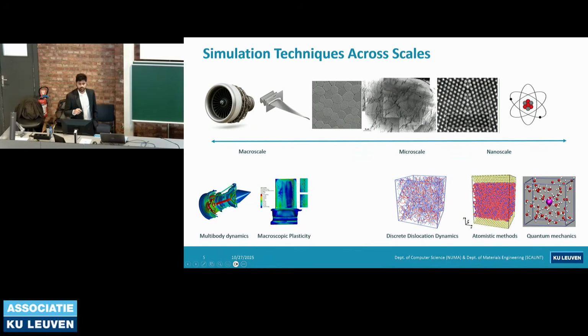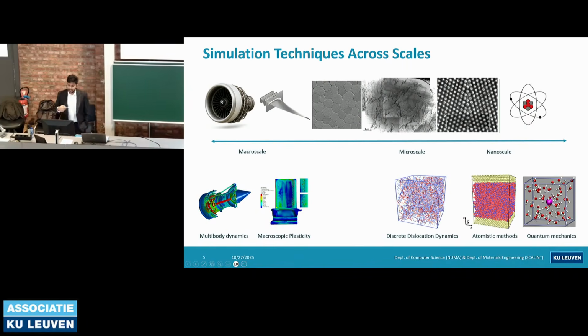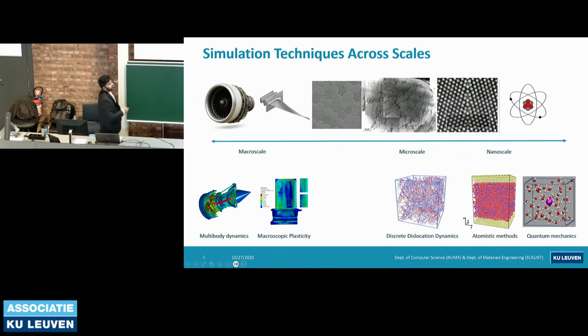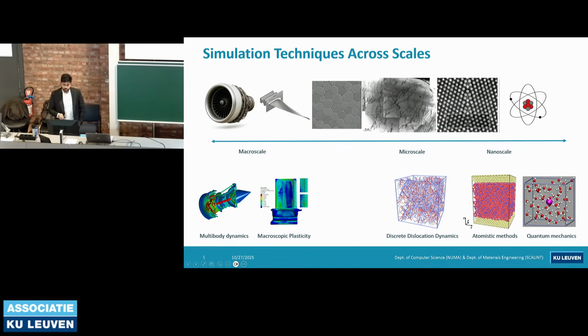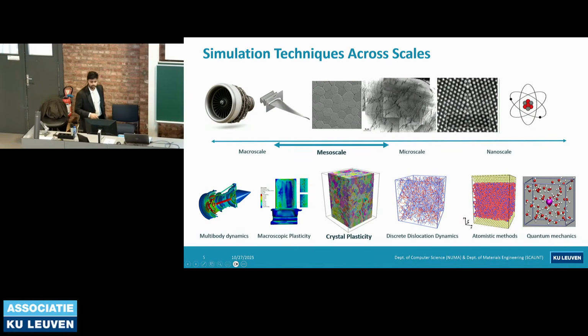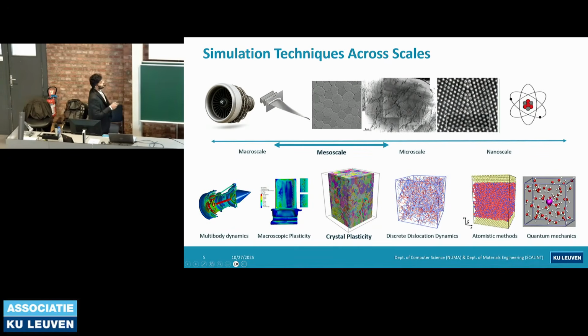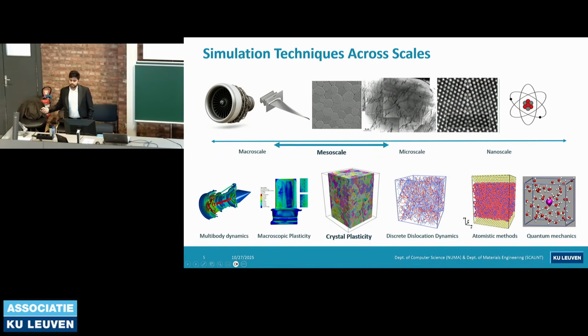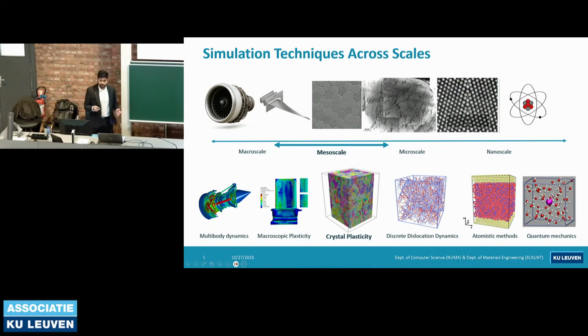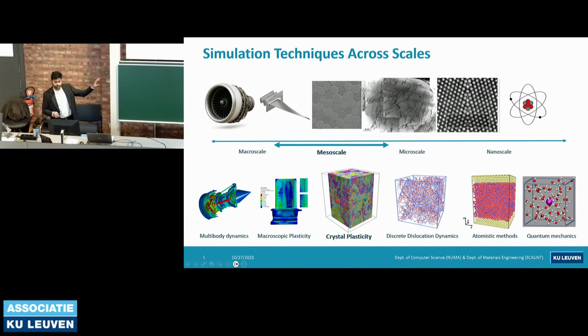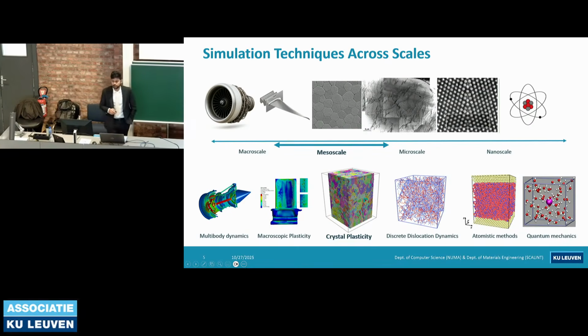But clearly, the simulation techniques on this end are quite practically applicable, and they can reproduce the realistic boundary conditions which are actually seen at a component level. But they lack predictive capabilities because they ignore the microstructural features. And the simulations on this end are quite physically grounded, so they are quite accurate, but they struggle to extend to larger volumes or to be practically applicable. So what comes nicely and ideally in between is mesoscale. Mesoscale simulations act as a bridge between the macro scale and micro scale. They try to capture the physical detail from the lower end simulations and also be practically applicable for the macro scale simulations. In this family of simulations for material deformation, crystal plasticity is one of the important simulation techniques.